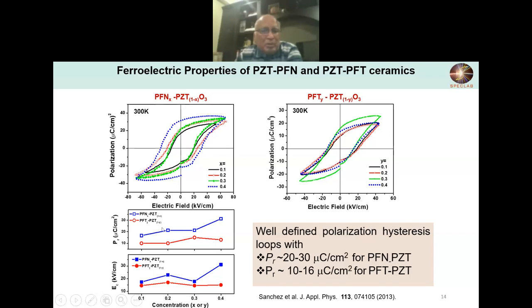You can see 0.2 and 0.3 here is considered the best, because you have to consider the two materials. One is PFT-PZT, one is PFN-PZT. This is PFN-PZT and this is PFT. So for almost every concentration there is a polarization, and it is quite reasonable. At least 0.3 is good for both of these materials. It's a reasonable value.